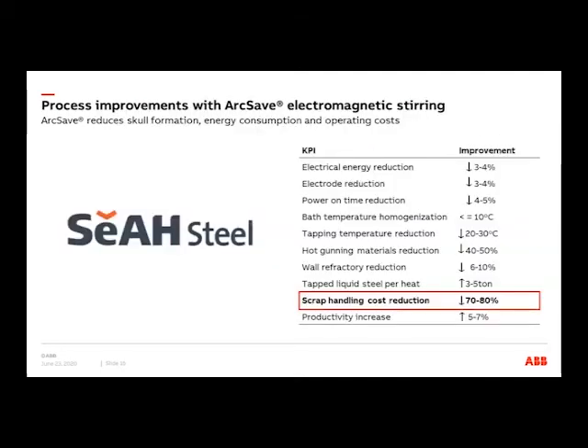On the next slide, you have a summary of the results which we got out from SeAH during the performance test. And just to highlight some of the results was, of course, the scrap handling cost reduction. This was reduced by 70 to 80%, due to that in this case they could charge much bigger sizes for scrap, and they needed much less cutting of the scraps, which was a considerable saving for them. Also, of course, they could increase the scrap volume in the furnace and tap on a higher heat size, due to that they could reduce the volume in the furnace.